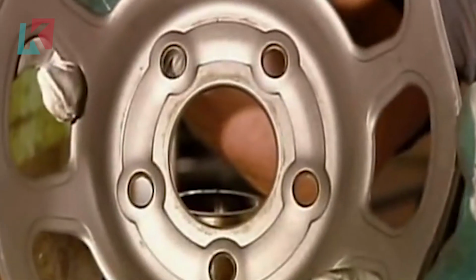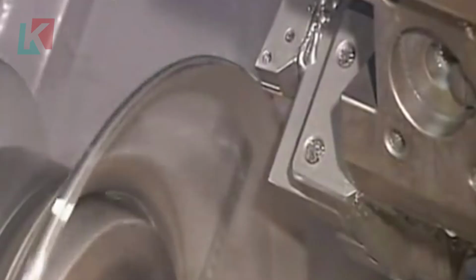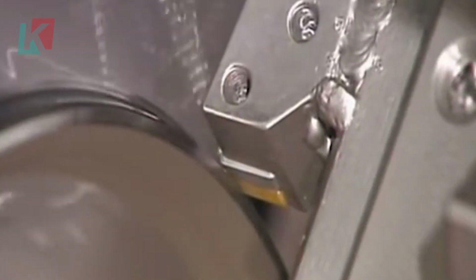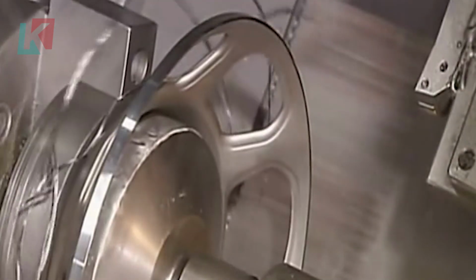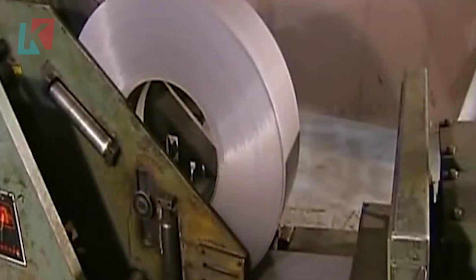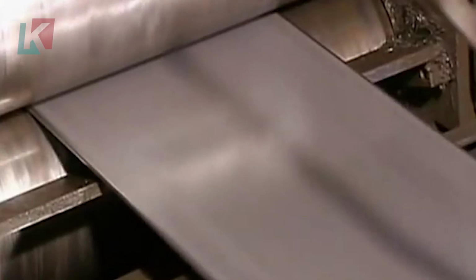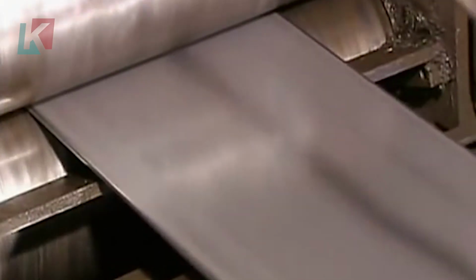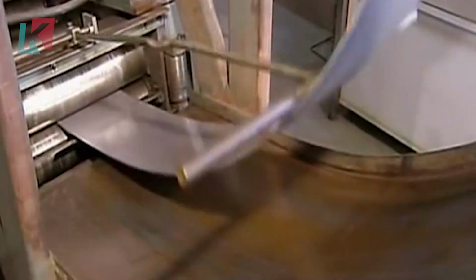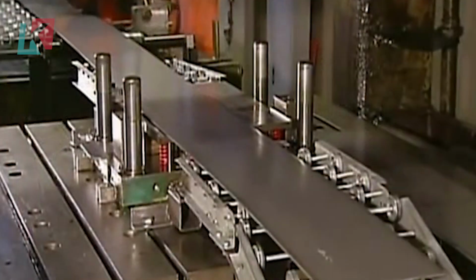of theoretical maximum. The casting dies themselves are masterpieces of precision manufacturing. CNC machined from premium tool steel and coated with specialized release agents, these dies can produce wheels with surface finishes so smooth they require minimal machining. Temperature control is absolutely critical. The aluminum is heated to exactly 700 degrees Celsius, hot enough to flow perfectly, but not so hot that it reacts with the die coatings. Infrared thermometers monitor pour temperature to within 5 degrees.